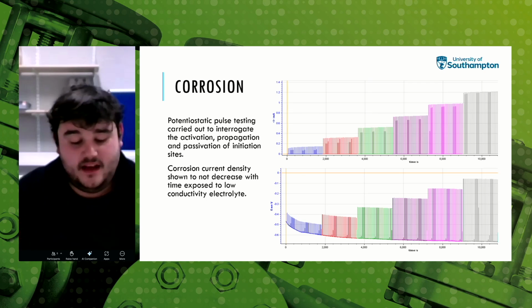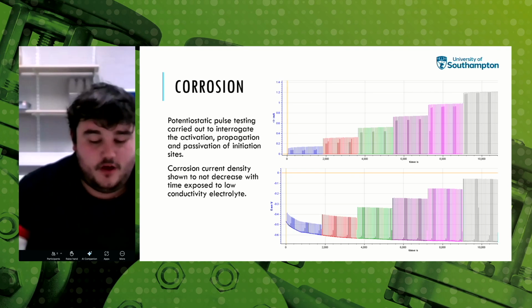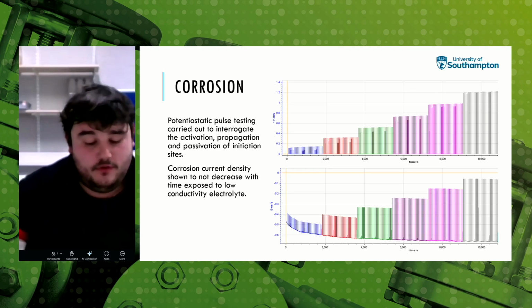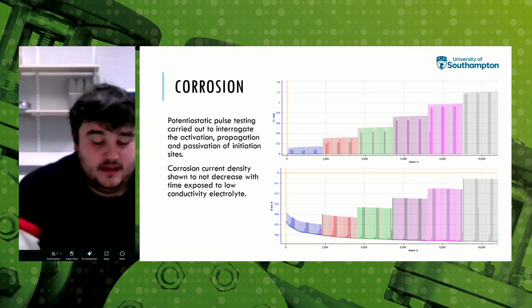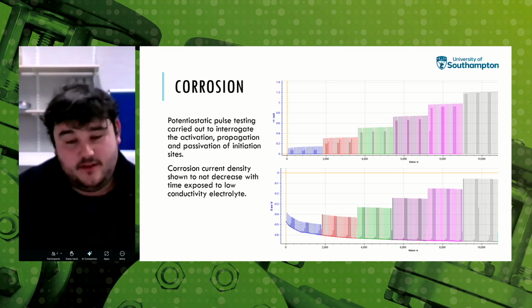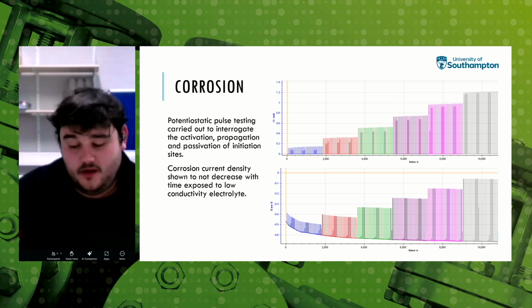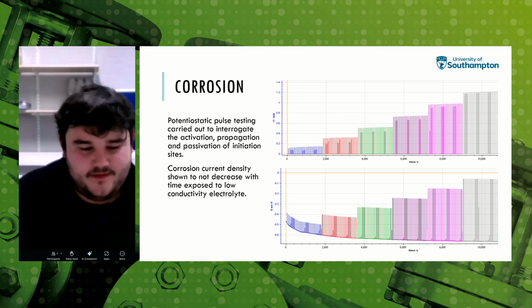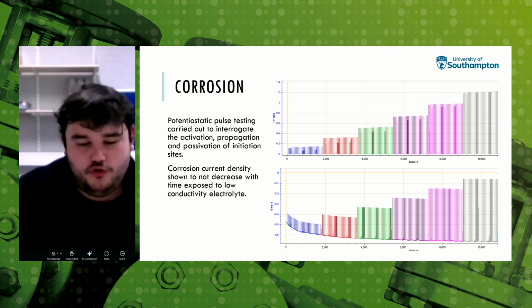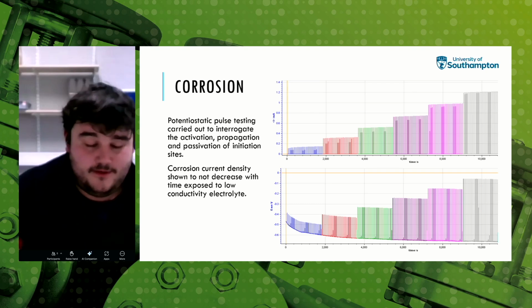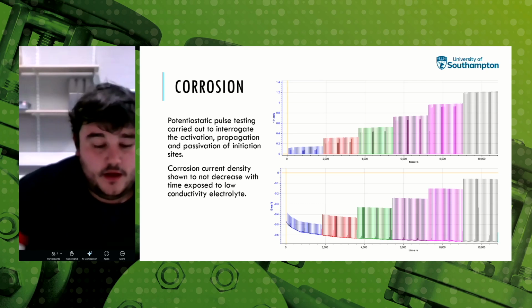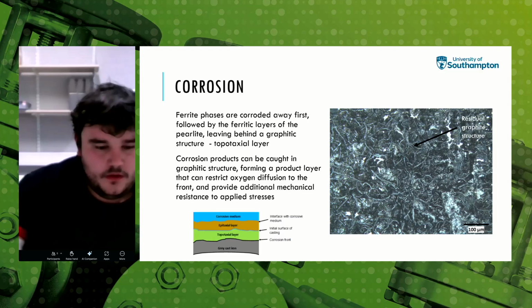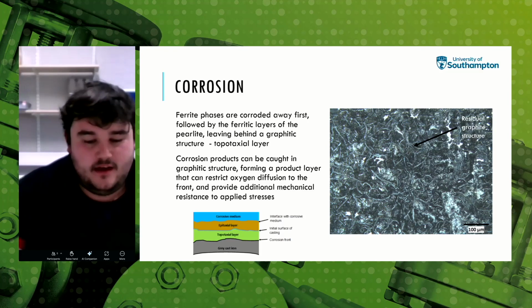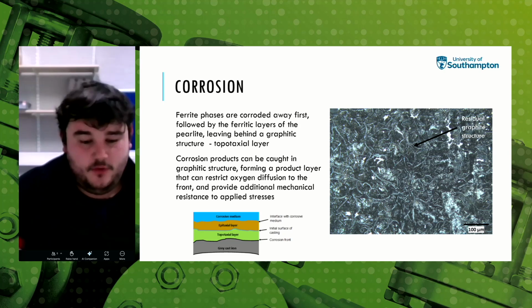We can see here in these graphs, as we increase the potential difference at which we energise the surface, the corrosion current density and therefore the aggressiveness of the surface damage increases at a commensurate rate. However, interestingly, this current density doesn't decrease over time. Just with these initiation sites, they don't passivate naturally as they would in, say, a carbon steel. They continue to propagate indefinitely, provided there's sufficient oxygen supply to the surface to sustain the reaction.